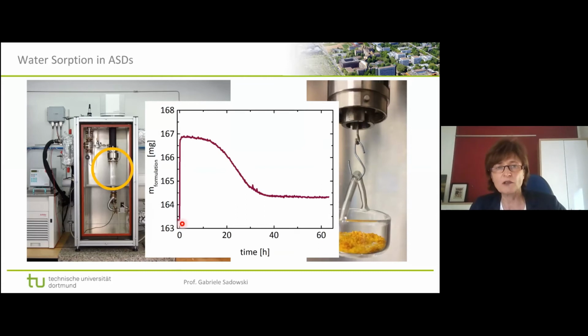You see the formulation at the dry condition. This is what the weight of the dry formulation was. And then we started the experiment, exposing the formulation to a certain relative humidity, and then more. Almost immediately, within 30 minutes, we have a huge water uptake. So that means this is really the absorption of water from the atmosphere into the formulation in the tablet, so to say.